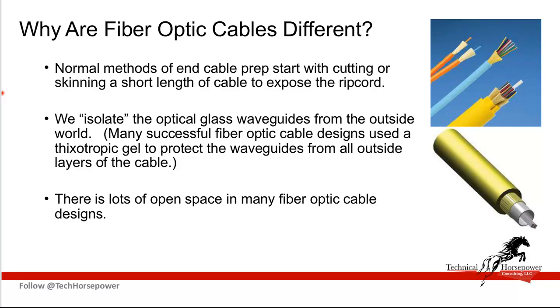You'll see in some of the pictures over here that there are a number of different designs that are indoor cables shown here. And now we are going on to high fiber count cables, to a number of central tube designs, which is this item down here, where you basically have a large tube and bundles of ribbons or loose fibers bundled up inside it. There's not a great deal of strength here, so when you're peeling off the jacket, you have the ability to kink these cables very easily. And a kinking of the cable is a significant problem.